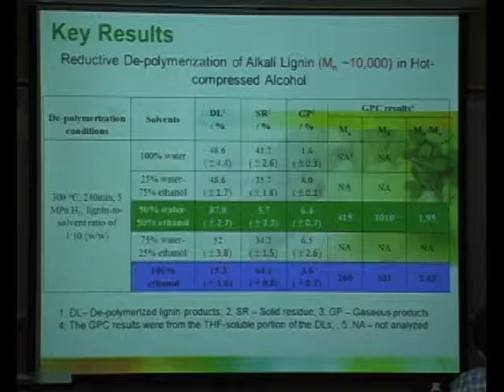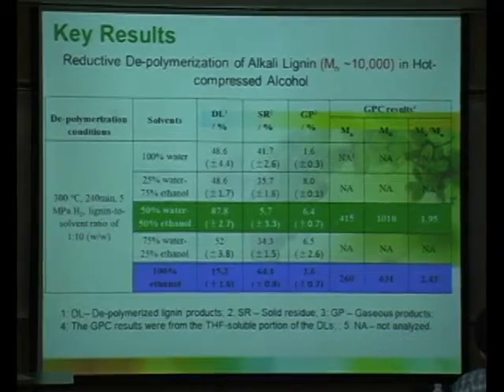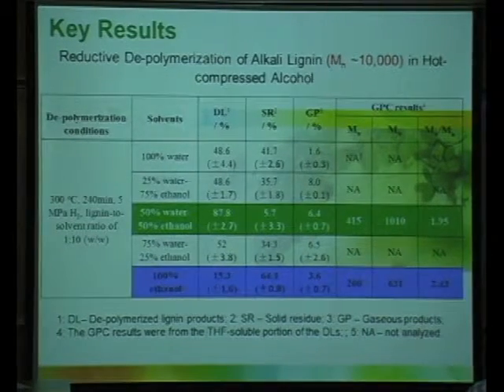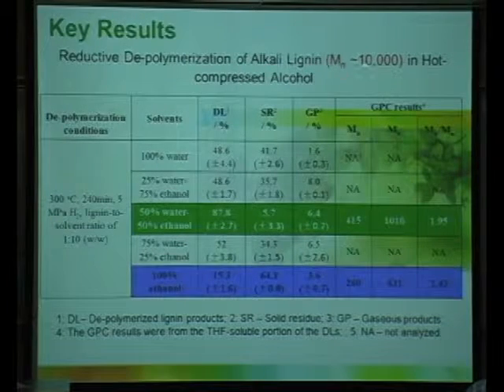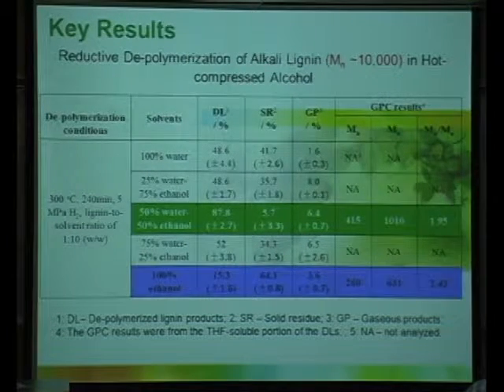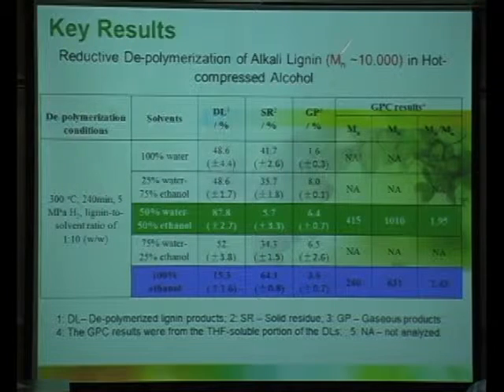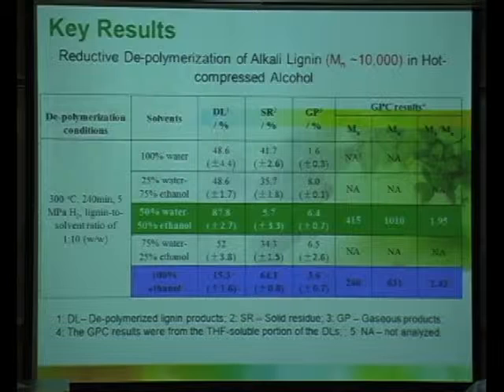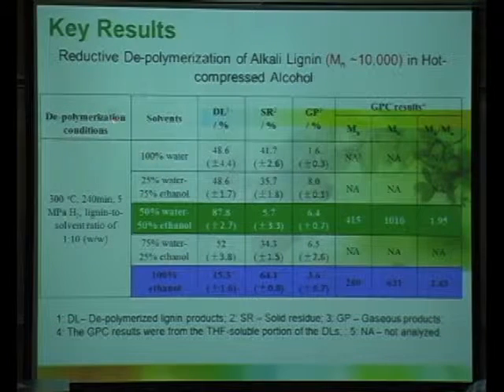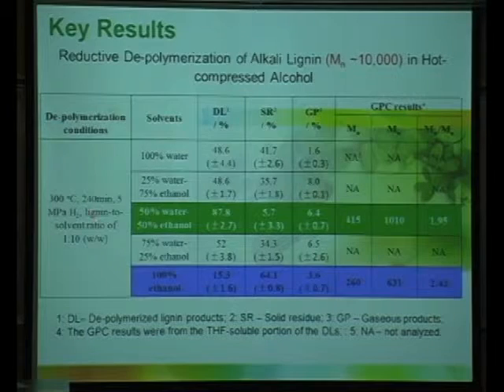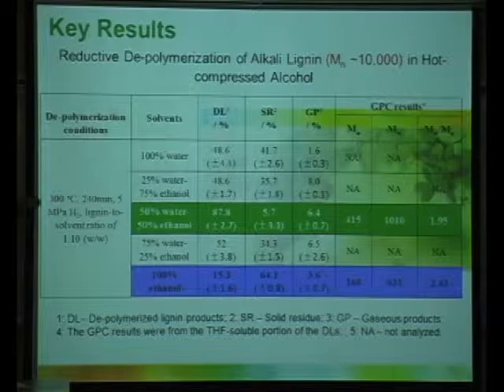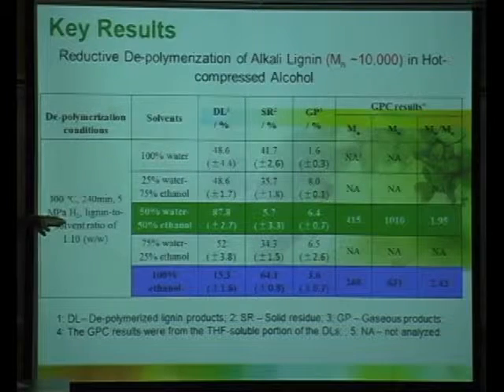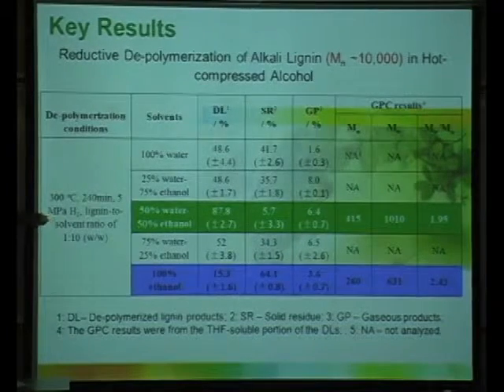Now, just some typical results for depolymerization, because I said that's more promising. We can depolymerize lignin, and this lignin comes from the pulping industry. After we produce paper, some lignin is waste material. We can get that lignin, which is alkaline lignin. The molecular weight is very large, about 10,000. We can break down those larger molecules into small molecules, biophenols, by the depolymerization process. This is a thermochemical process involving a temperature of 300 degrees C and hydrogen as a reducing agent. So this is reductive depolymerization.